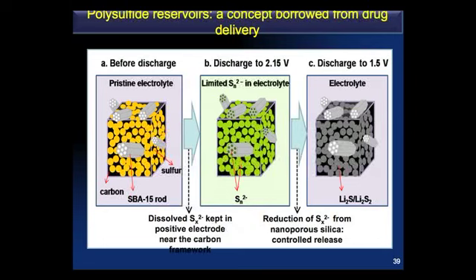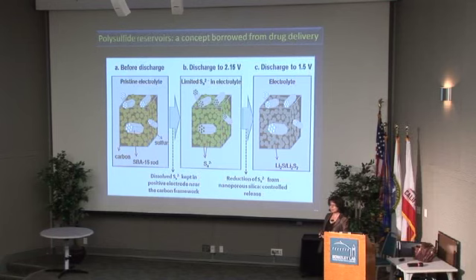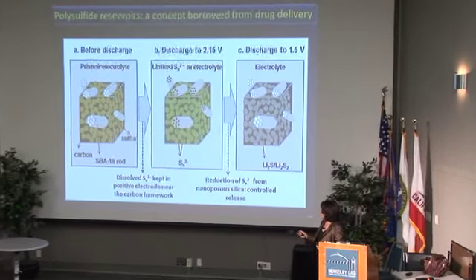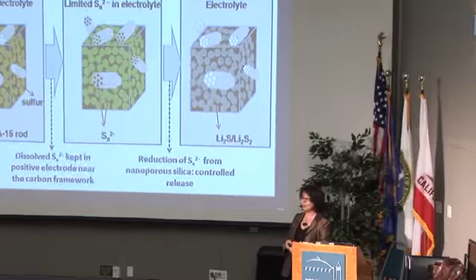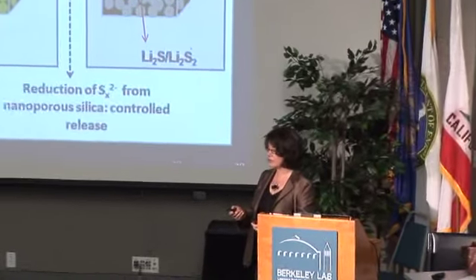What we learned when we did this is that we had quite a problem with polysulfide diffusion, because now we have these 12 nanometer pores and a lot of the sulfur on the outside was escaping. So we borrowed a concept from the drug delivery folks, the pharmaceutical people, who use this material, SBA15, which coincidentally is the silica that we actually used to cast the carbon in the previous studies I mentioned. These are mesoporous silicas that have pore dimensions somewhat along the same dimensions as the polysulfide anions.